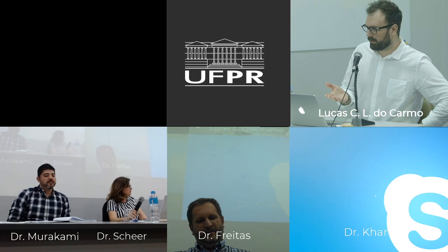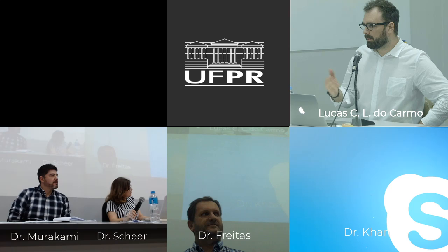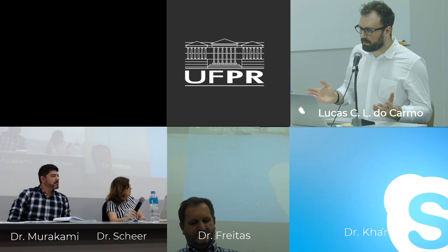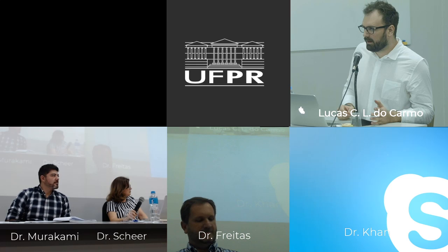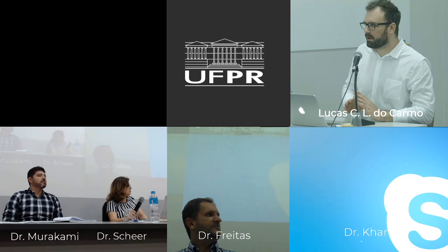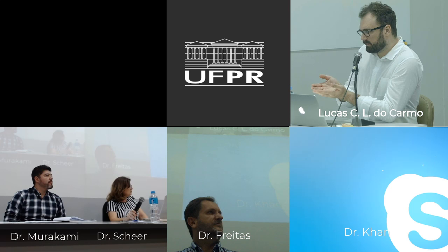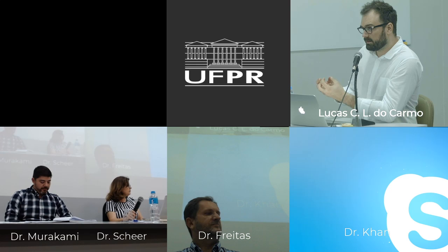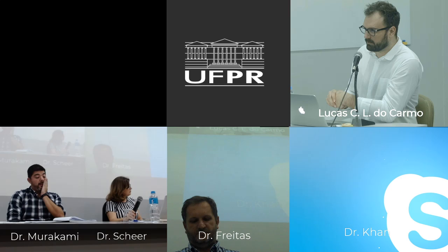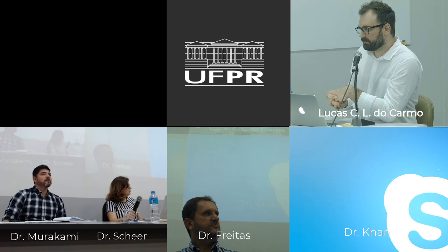Now, there are other things in rheometry that I obviously thought about more, like choosing a better geometry. The cone plate geometry is perfect for measuring viscosity in liquids, but it's not very used for oscillatory rheometry. It can be used, it's not wrong to use, but since you have a defined gap that you have to use, then you should use a plate geometry with a higher gap, because in some cases I had droplets that were over the gap of my rheological experiments.